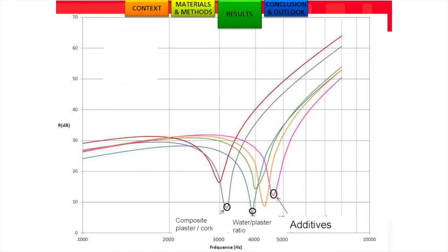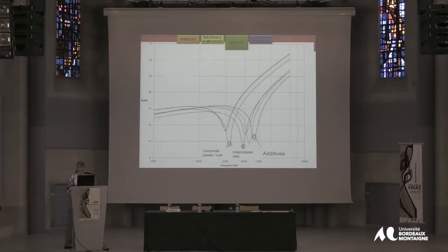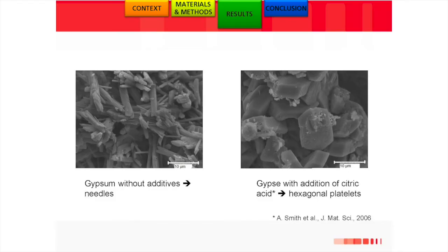Here are the experimental results we obtained: transmission loss as a function of frequency. In red here you have a commercial product, with a critical frequency of about 3000 hertz. If we add cork, not much change - we even decrease the critical frequency. If we increase the water over plaster ratio, we shift the critical frequency, but we decrease the mechanical strength. The best result we obtained was with the addition of additive, because the flexural strength was maintained, and we managed to shift the critical frequency to about 4500 hertz.